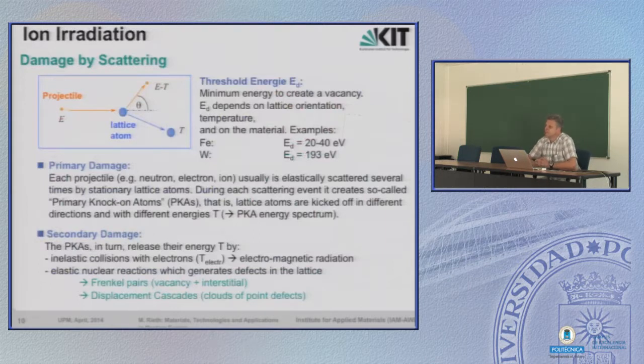Now let's first focus on ion irradiation, because that's more simple. If you consider a fast ion emitted from a source and hitting a metallic lattice, what happens? If you are used to play pool billiard or so, you already know all the answers, because the same is happening in any lattice. You have a projectile or a ball with a kinetic energy E, and it hits somewhere a lattice atom and is scattered, facing a loss of its energy. The loss of energy has been transferred elastically to the lattice atom, which is also displaced from its lattice place, and this has the energy T.